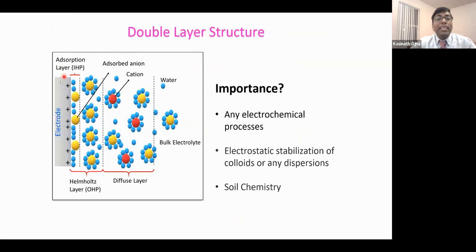So let's say you put an electrode inside an electrolyte having ions and solvent. So there is a mixture of ions and solvent solution. Depending on the charge of the electrode, a layering of ions will happen. If your electrode is positively charged, the anions will come close to the electrode, and there will be a distribution of ions. If it is negatively charged, the cations will come close. And of course, when you put an electrode into the electrolyte, there will be a solvent layer on the electrode.